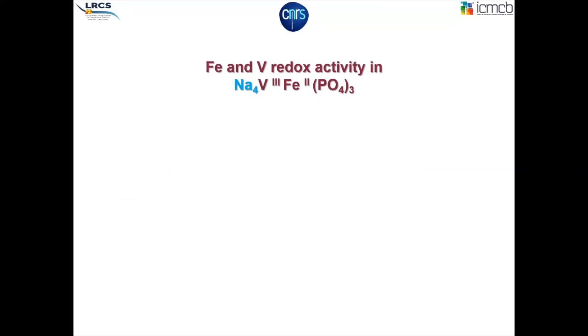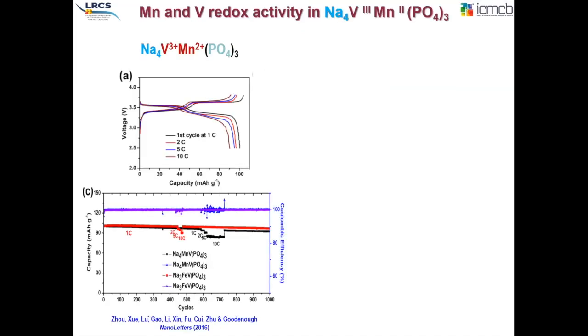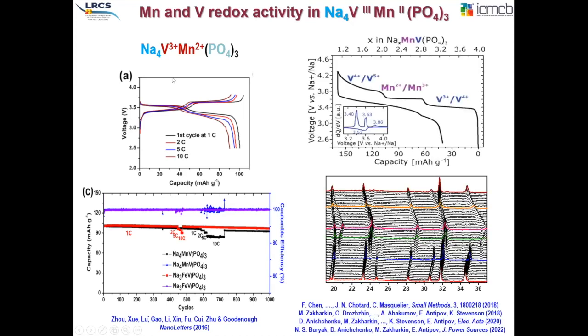I will move on to the last small part of my talk towards the new studies we recently performed around the substitution of one vanadium by one iron to lead to the Na4 FeV PO4 three times cathodes. Several groups, including co-workers with John Goodenough, have been working on substituting vanadium by different elements, such as manganese, to lead to these very impressive electrochemical properties when the operating voltage is limited to 3.7 volts versus sodium.